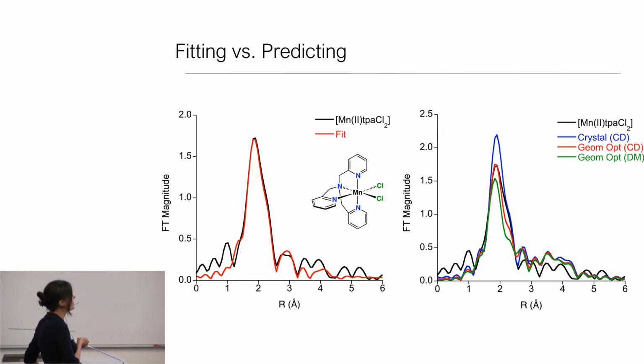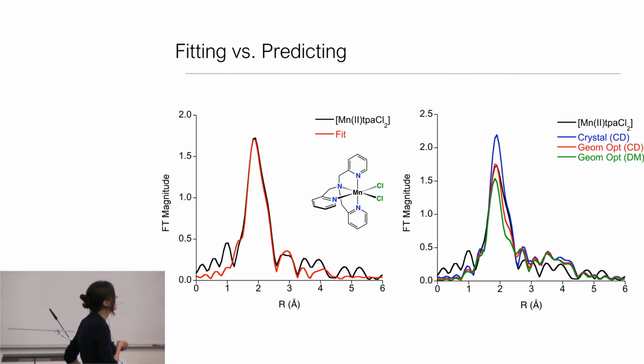But we can also just take direct FEFF calculated parameters, either at the crystal structure, which is in blue. That looks a bit off from the experimental data. I can geometry optimize in ORCA and then use FEFF to do correlated Debye calculations. That's red. That actually looks quite good. But if I geometry optimize and do a more sophisticated treatment of the Debye-Waller using a dynamical matrix method and a DFT-based Hessian, it actually gets worse, which is interesting.